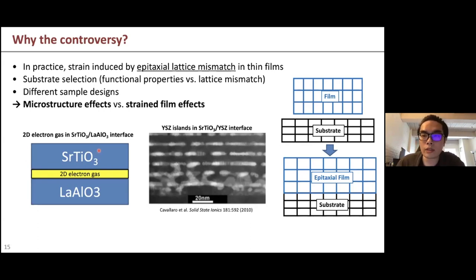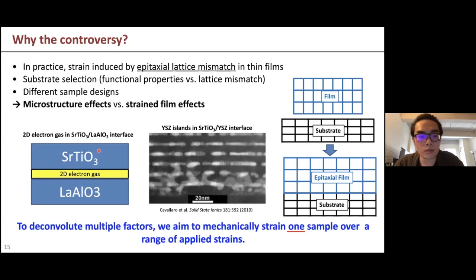So in the end, due to this technique of how people apply the strain, the final result will be a competition between the microstructure effects and the strain effect. So in this experiment setup, we want to deconvolute the different factors. We aim to mechanically strain only one sample over a range of strain.